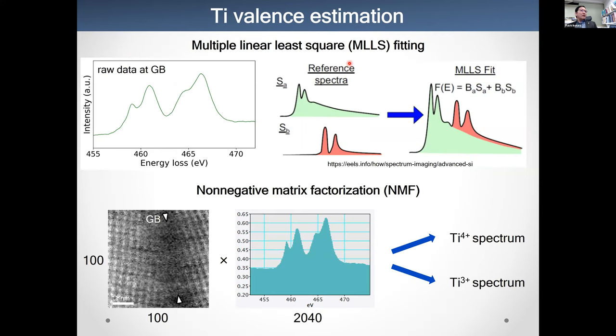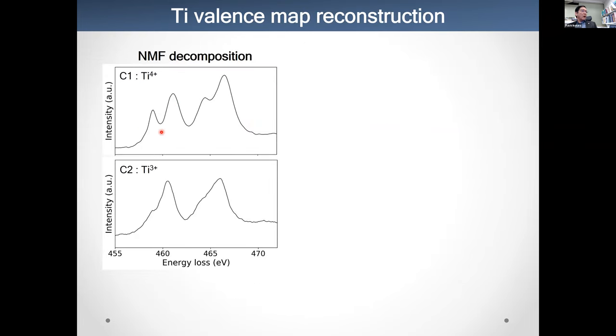And we estimate the titanium valence. Usually, we use multiple linear least squares fitting, with which we can separate the two peaks like that. But this time, we applied the non-negative matrix factorization, NMF, method, because we have a lot of spectra from each pixel. So we can divide the Ti4+ spectrum and the Ti3+ spectrum by this method. This is the obtained NMF decomposition spectrum for titanium 4+, and this is titanium 3+.